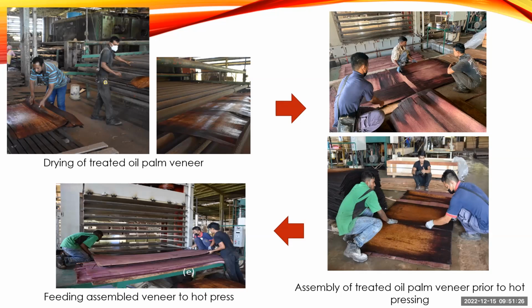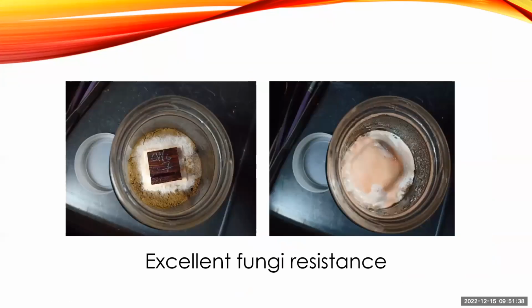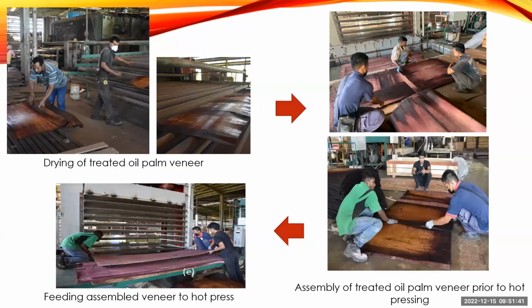After pre-drying, this is the assembly of the treated oil palm veneer prior to hot pressing, and then we feed the assembled veneer into the hot press. This is the upscaling treatment conducted at a local manufacturer in Malaysia.